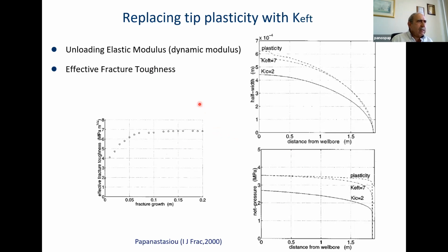What I will advise for the practitioners is to use the unloading elastic modulus in the classical hydraulic fracture simulators. The reason for using the unloading elastic modulus is because near the fracture tip we have plasticity, but once the fracture propagates, the region behind unloads elastically. So the bulk of the area is under unloading mode. So use the unloading elastic modulus, which is very close to the dynamic modulus and actually quite easily available in the petroleum industry, and take care of plasticity with effective fracture toughness.